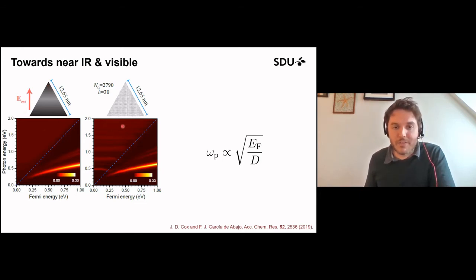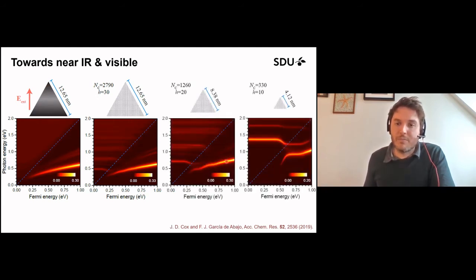But you can see a difference if you do the simulation atomistically, using even just a simple tight-binding model, but you include a self-consistent electron-electron interaction. And typically the plasmon energy scales with the Fermi energy, and inversely with the size of your island. So if you keep making it smaller, you can start to push the resonance to higher and higher energies. And here, by the way, I'm plotting the absorption cross-section of the island. So you see a strong feature where the plasmon resonance is.